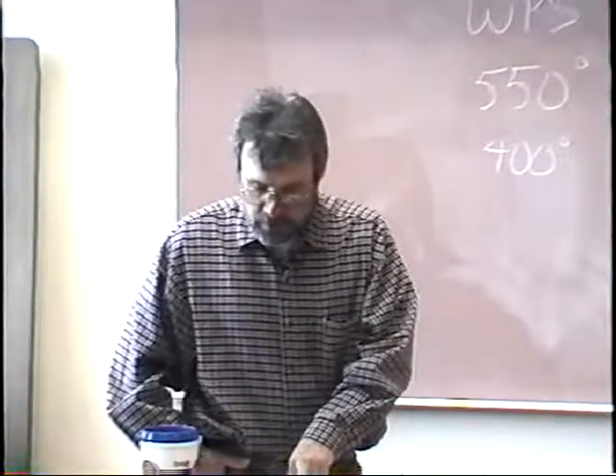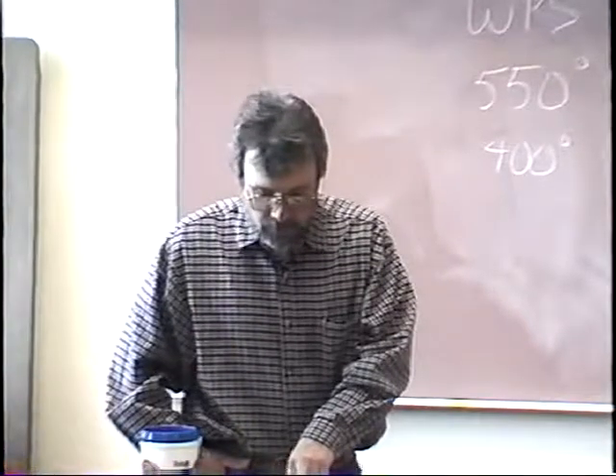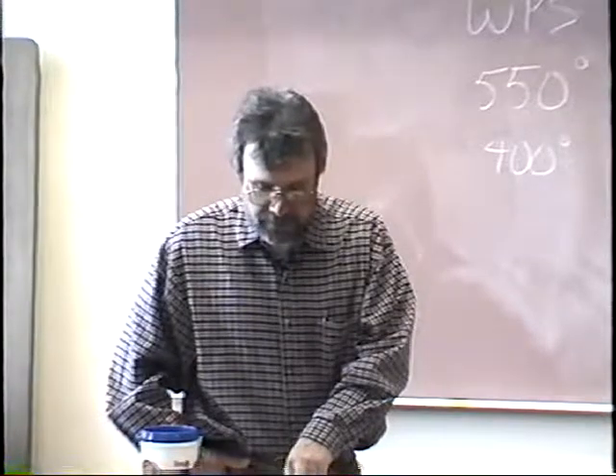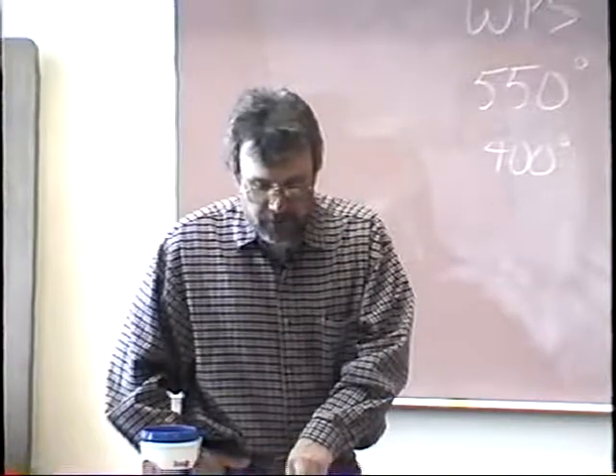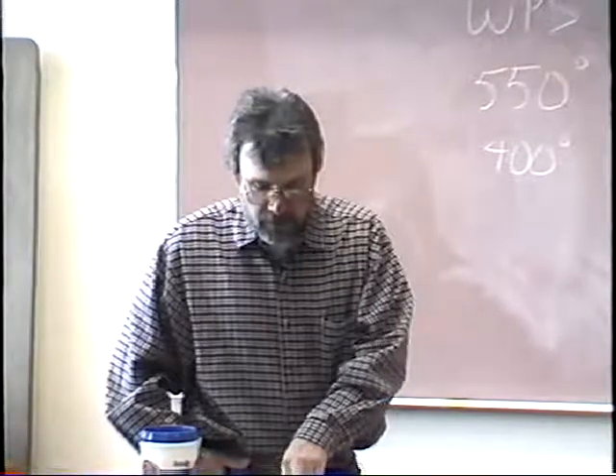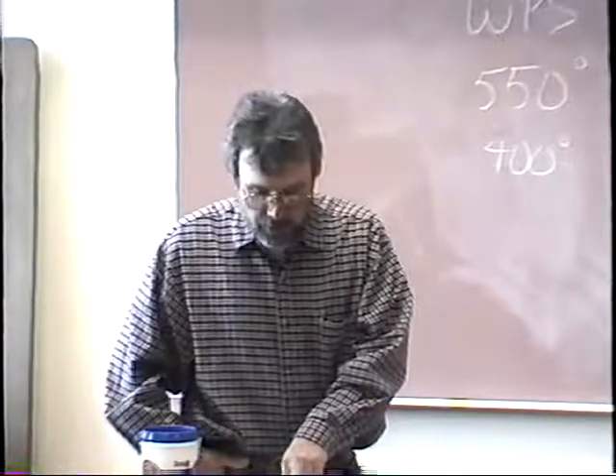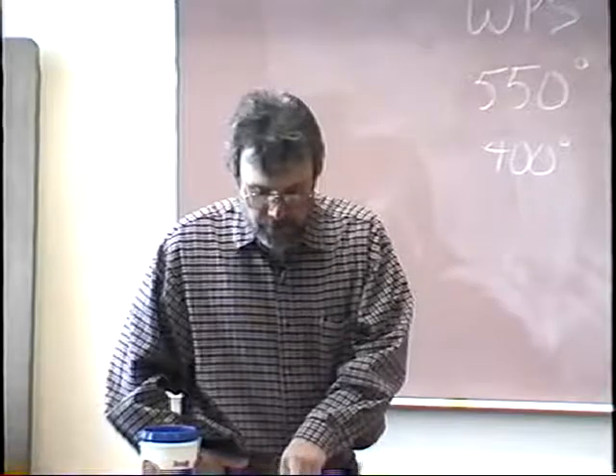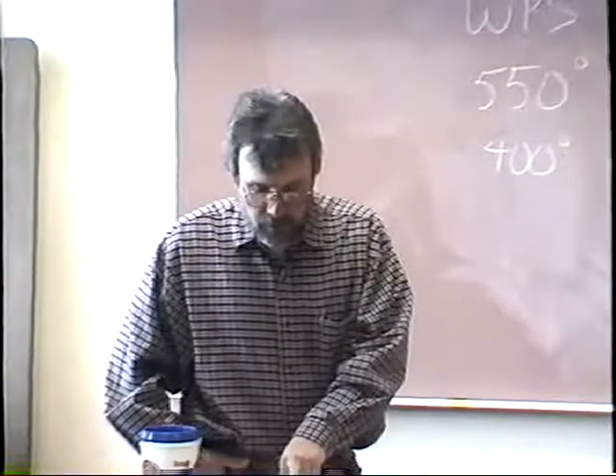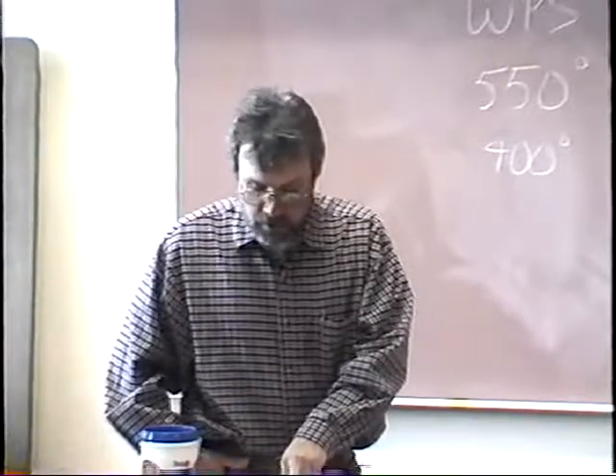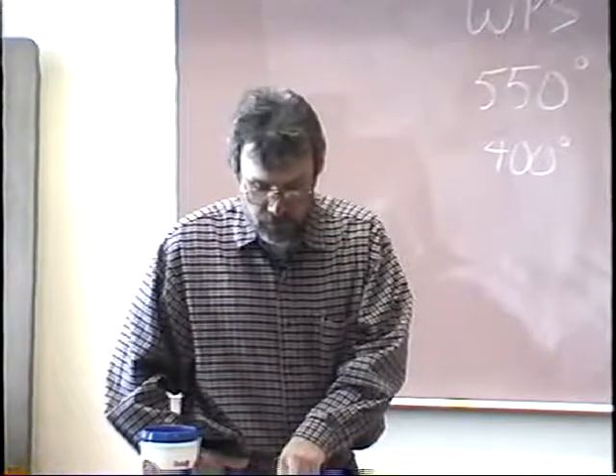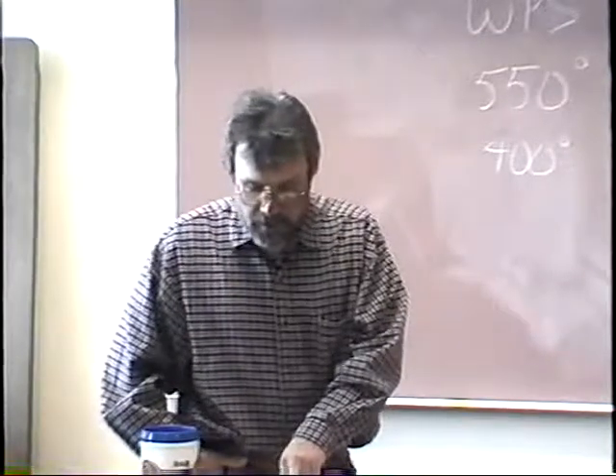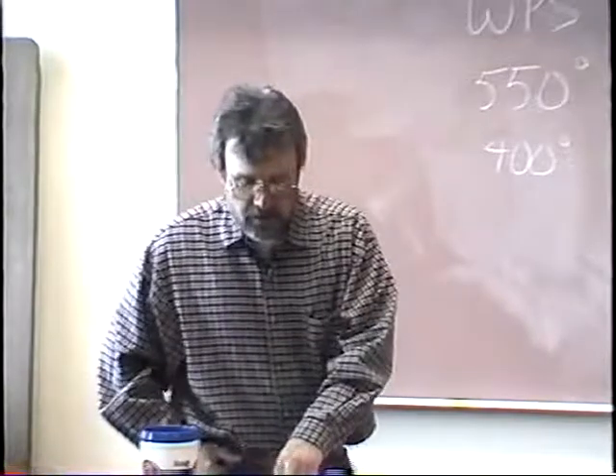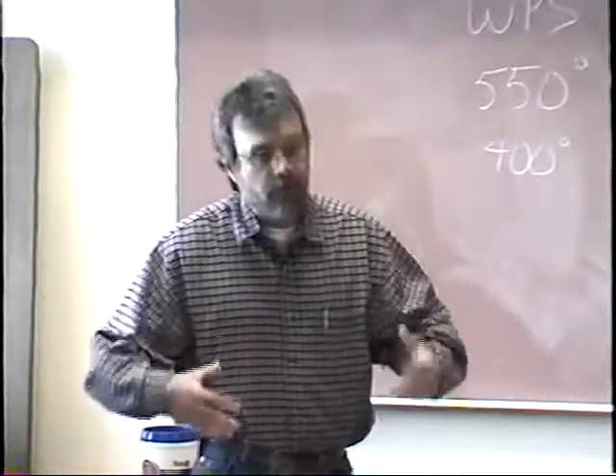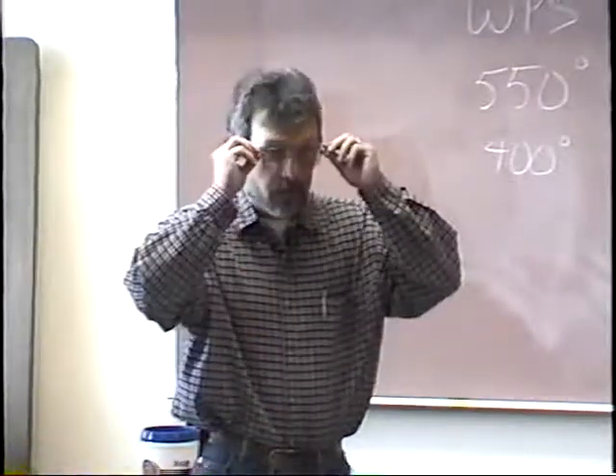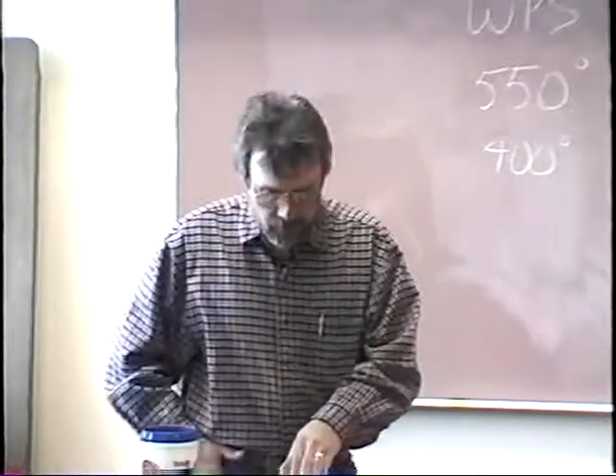The application of supplementary heat to the joint before welding is an important part of the welding procedure. It elevates the temperature of the pipe immediately before welding and is called preheating. Preheating lowers the cooling rate as the welding arc moves along. For a given set of welding conditions, such as current setting, speed of travel, and material thickness, the cooling rate will be faster for a weld made without preheating than with preheating. So it's going to draw off that heat a little bit better, give you better properties, less possibility of cracking, less residual stress in there.